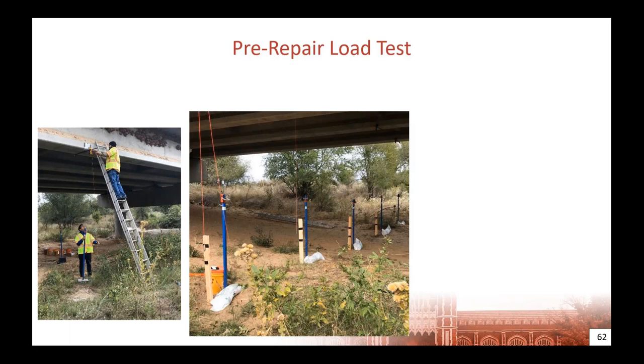So before construction started, we went out to the Wolf Creek Bridge and we instrumented it under span four. It was the easiest span that we could get to. Unfortunately, water was over under span three, and then the joints between span two and three were also over water, so we couldn't instrument those for the later testing. So we just stuck with span four, and we instrumented each of the girders to monitor deflections for the pre-repair test, since we had no access to the inside of the joint.